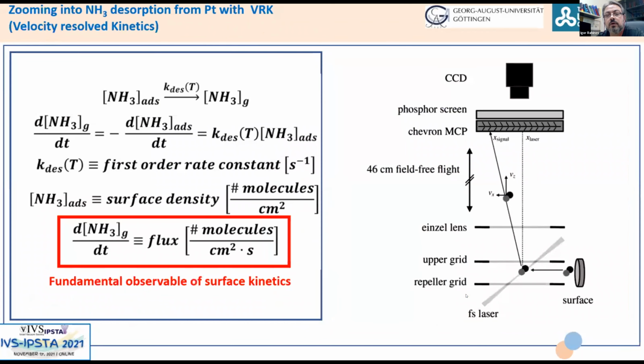A good starting point is to look at something which is even more basic than the reaction of ammonia with oxygen on a platinum catalyst: to look at ammonia desorption. So, a seemingly simple experiment, right? What is actually our fundamental observable in such an experiment? If we do some very simple dimensional analysis of this first order process, we see that this is the rate of appearance of ammonia in the gas phase. This is the depletion of the ammonia adsorbate. This is the first order rate constant. And this is the surface density of the adsorbate, which means that what we need to detect is the flux of molecules, basically the number of molecules per unit area, per unit time.